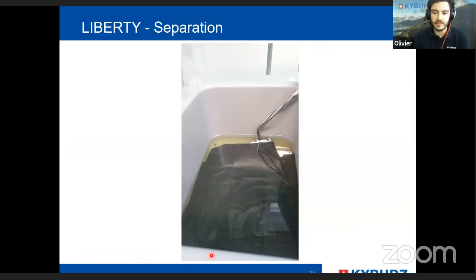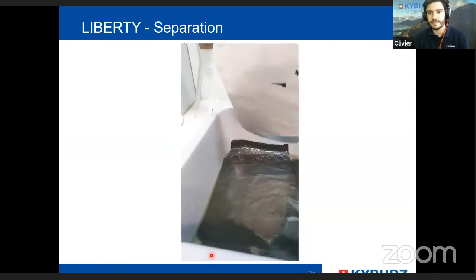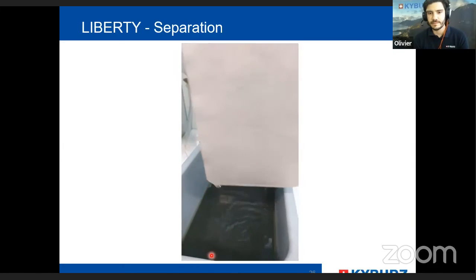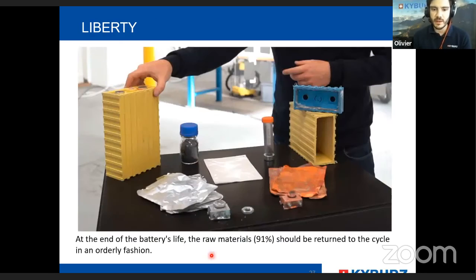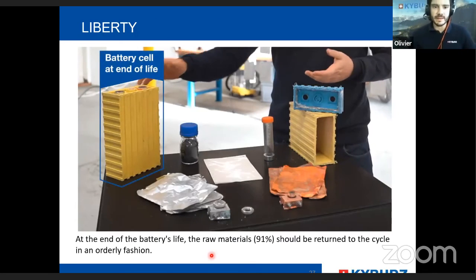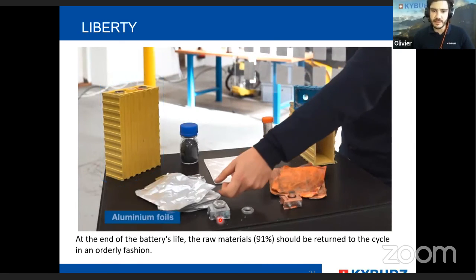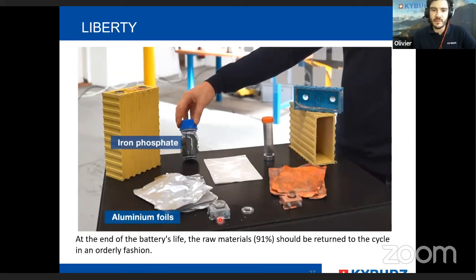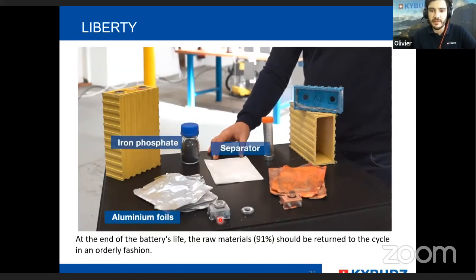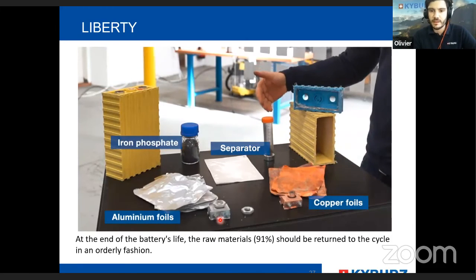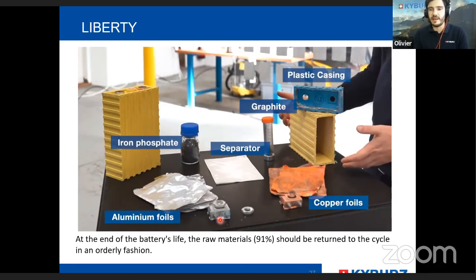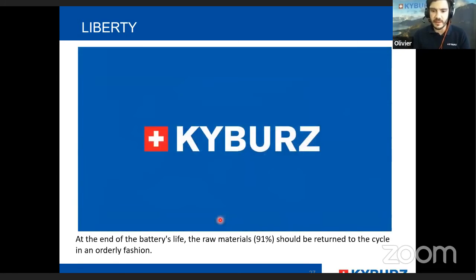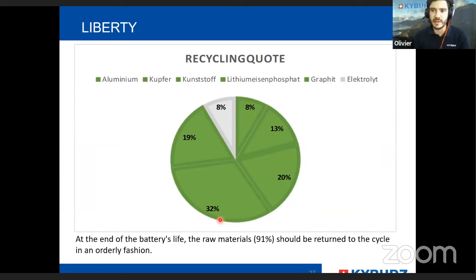And if we take the whole plate, it looks like this. So at the end, from one cell we have very clean aluminum foils, lithium iron phosphate, the separator, the graphite and the copper foils, and of course the plastic case. With this method our recycling quote is over 91%. What we cannot recycle at the moment is the electrolyte inside. And the next step will be closing the loop with these materials.